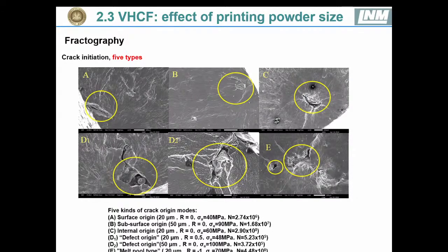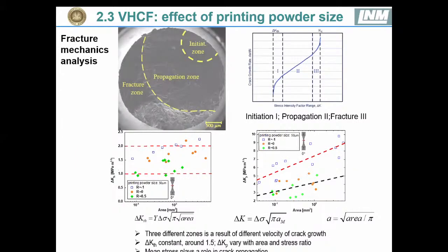We can also see that the crack may start from the melt pool, shown in figure E, and also several cracks, multiple cracks, could be found, as shown here in figure E. And these crack initiation modes are somewhat different from those in traditional manufacturing specimens. Fracture mechanics analysis will be used to study crack initiation and propagation.